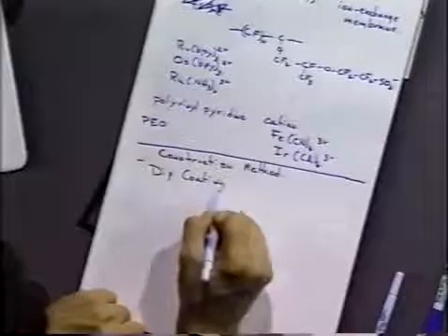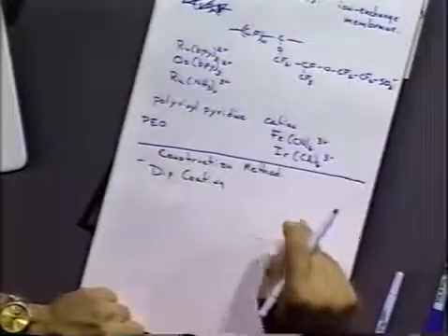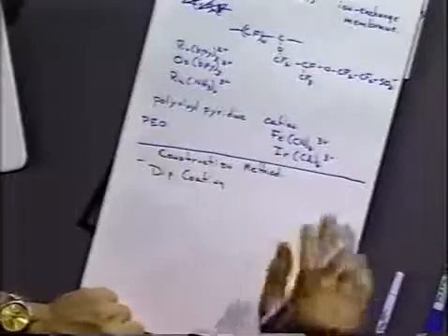The idea is you put the polymer dissolved in a suitable solvent at a certain concentration, you dip your electrode into the solution, and a thin film of solvent plus dissolved polymer is incorporated as a thin film of solution on top of the electrode. Then you allow that to evaporate, and the solvent evaporates, leaving the polymer behind to form an adsorbed polymer layer.